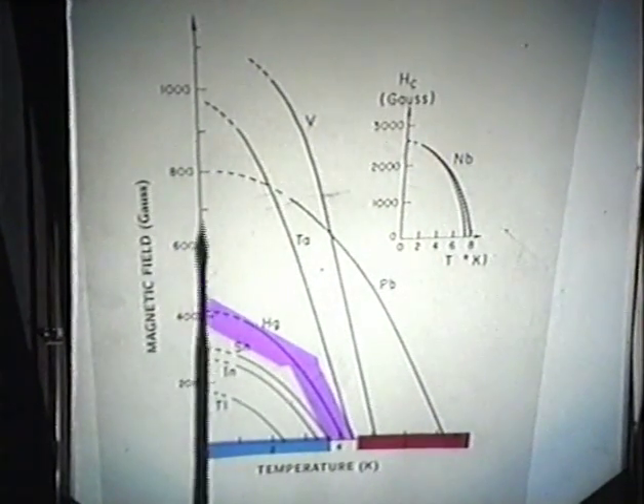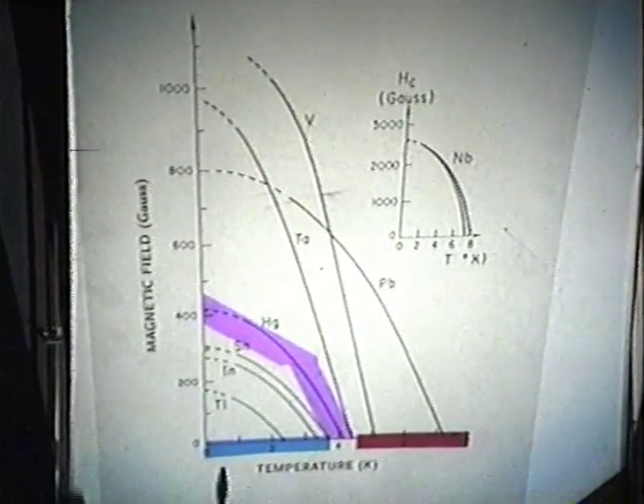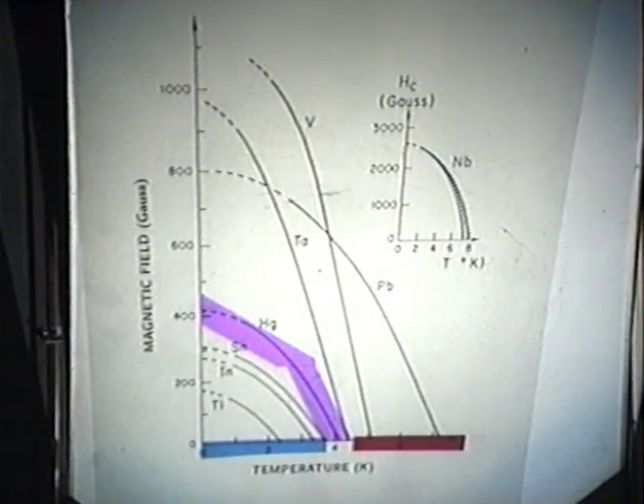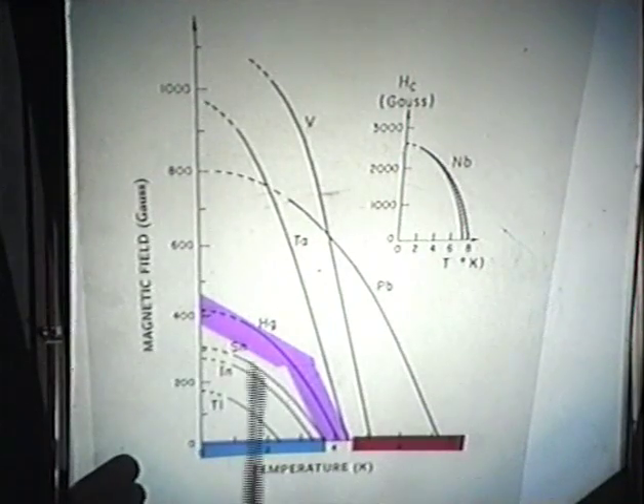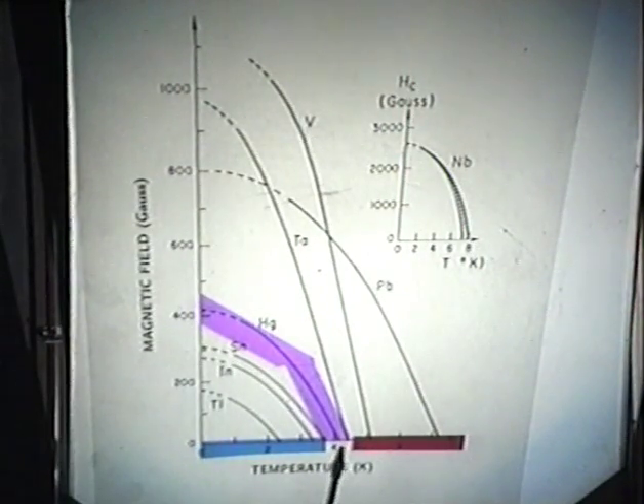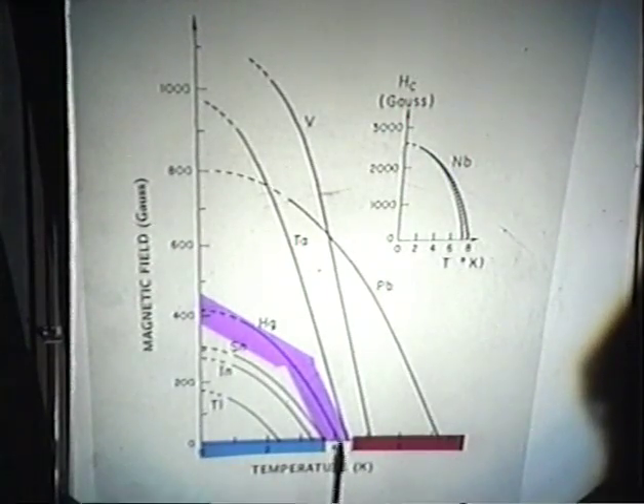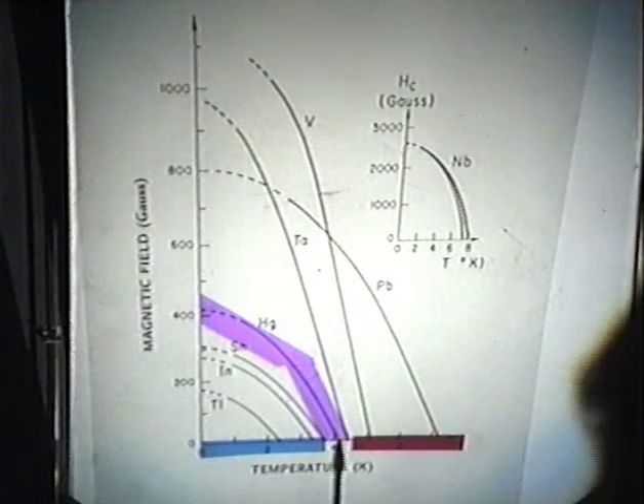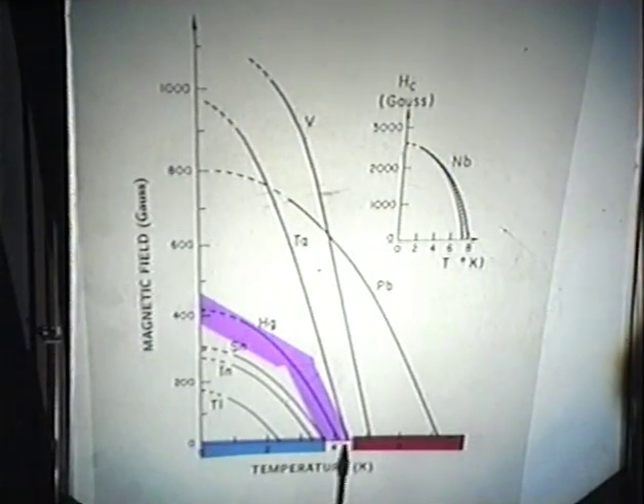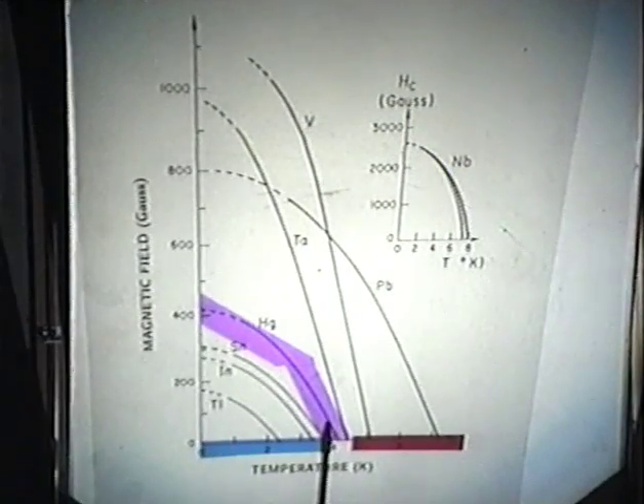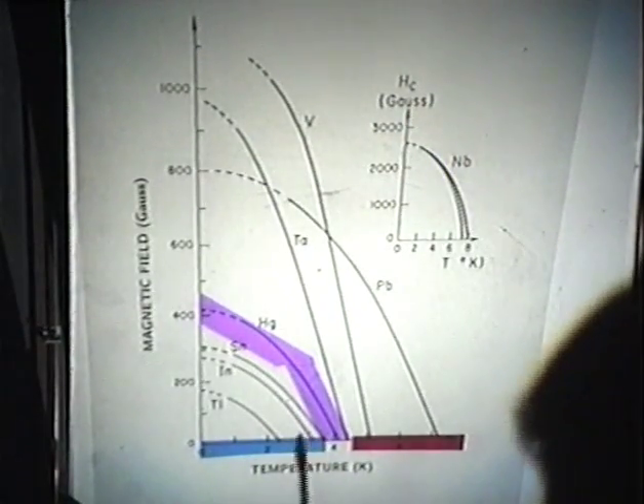So just to summarise those measurements, I can show you what I call the superconductivity phase diagram. Right, I've got a little job for the cleaners there tomorrow. Okay, so what we've got here is a magnetic field applied to the superconductor on the vertical axis and the temperature at which you cool the superconductor down along the horizontal axis. And you find that, for example, mercury, which I've highlighted here, which goes superconducting in the absence of a magnetic field at about 4 degrees above absolute zero, can be destroyed by a relatively weak field, but you can repair the damage by simply lowering the temperature and it returns to the superconducting state.